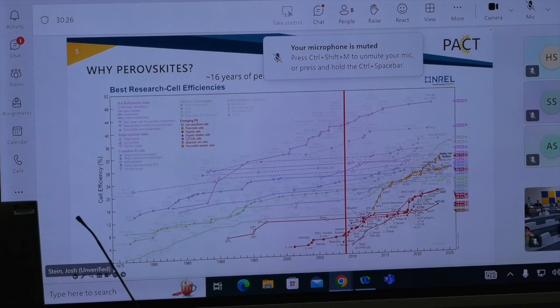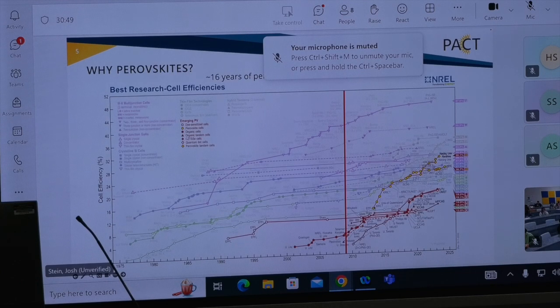And the diamonds are tandem structures. So a perovskite solar cell on top of another type of solar cell, which could be perovskite as well, or crystalline silicon, and it's reaching 30.1%. And so you can see that the slope of this line compared to the slope of this line is much steeper. And this is part of the reason why there's a lot of excitement, because in much less amount of time, the efficiency has risen to basically compete with crystalline silicon solar cells.